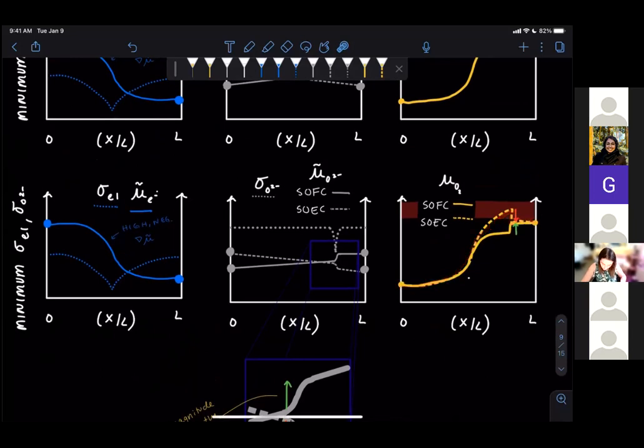And so now we've entered this red zone here. This red zone is basically anything up here is going to be an issue, and anything down here is going to be an issue. Up here, that means that you're producing oxygen. You can make an oxygen bubble within your solid electrolyte. And down here, it means that maybe you're creating a void. And again, these are all anomalies in your YSZ that you do not want because basically it's some sort of transport bottleneck that is causing some sort of energy to go into putting things where you don't want them.